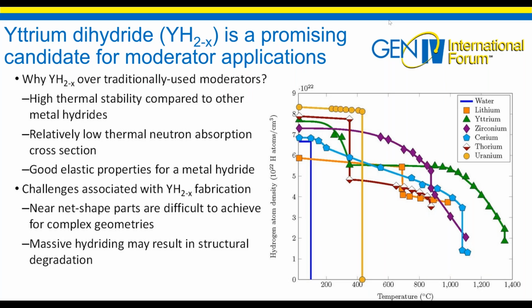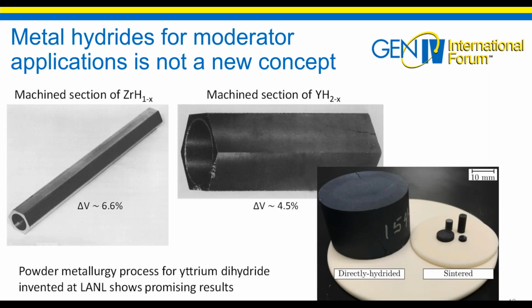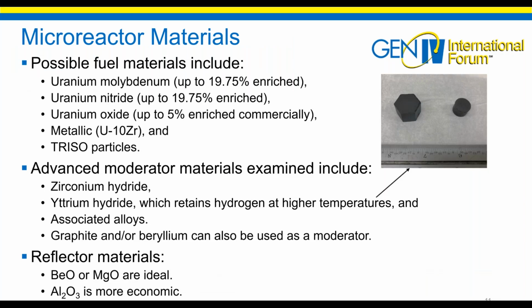First, the fuel types being examined include uranium, molybdenum, and nitride, with enrichment up to about 19.75%, otherwise known as high-assay, low-enriched uranium fuel. Uranium oxide that is commercially fabricated with enrichment below 5% could also be of interest. Finally, metallic and TRISO fuels offer potential.